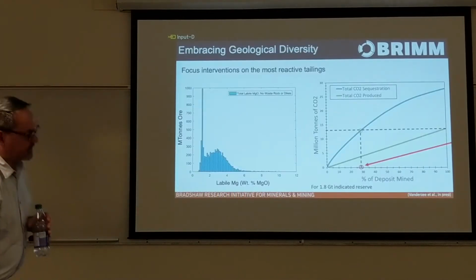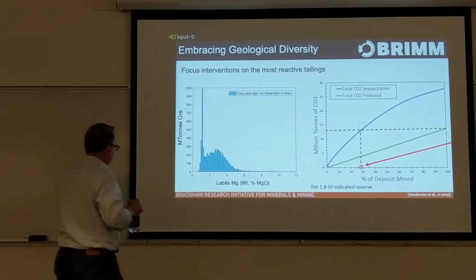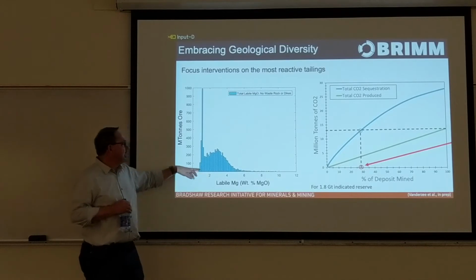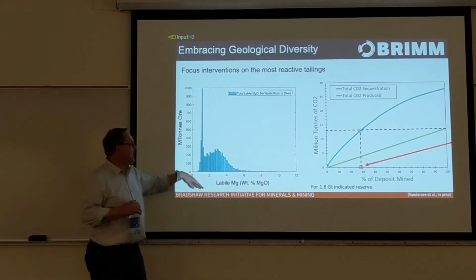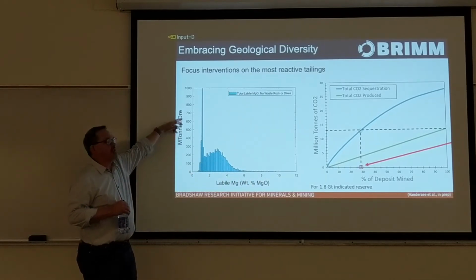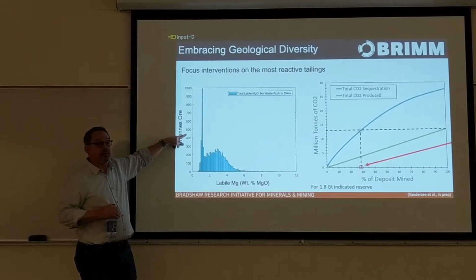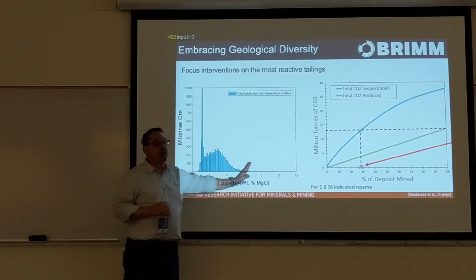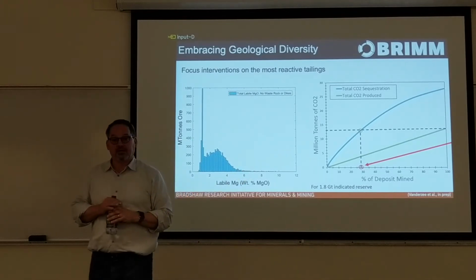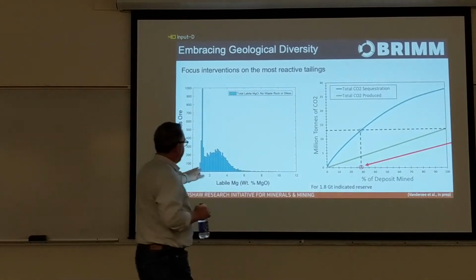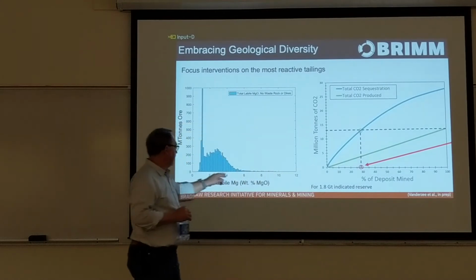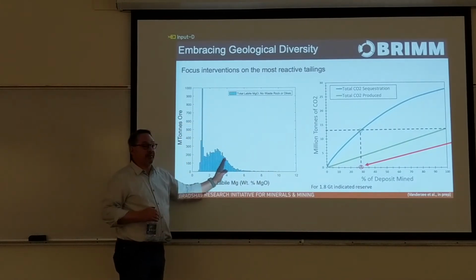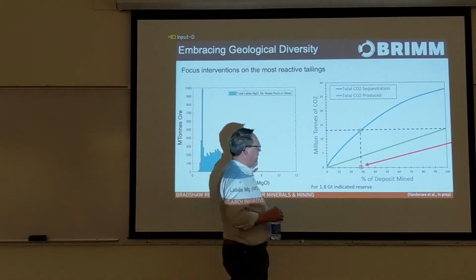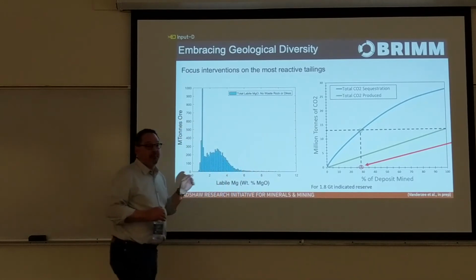So we can then apply that to the exploration geochemical database. Now this is the Baptiste nickel deposit in central BC, with labile magnesium content calculated from drill core and extrapolated into the whole ore body, about a 1 billion ton low-grade nickel deposit. So we now have millions of tons of ore at various labile magnesium contents. The important thing to take away is that there's a long tail out here, and we still have an average, but we have a significant amount of material that has a high labile magnesium content.